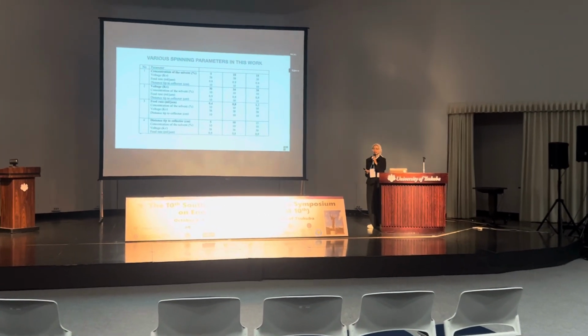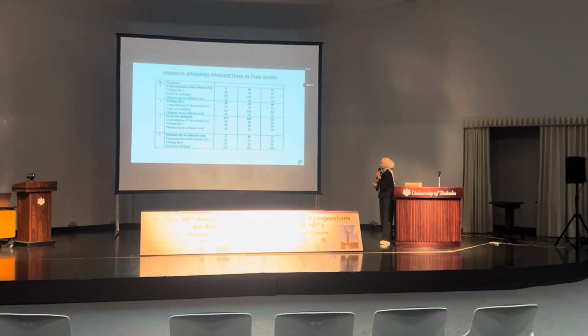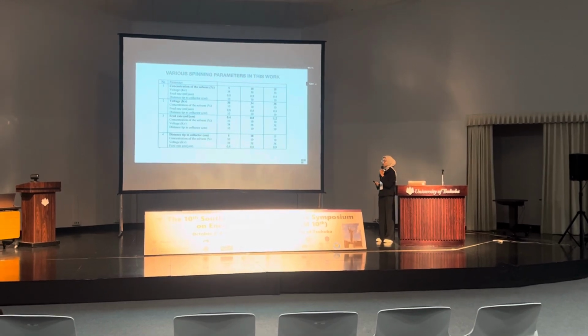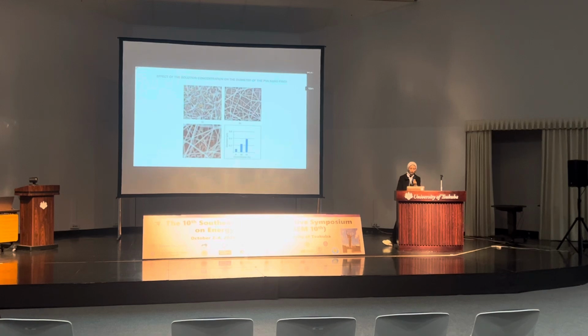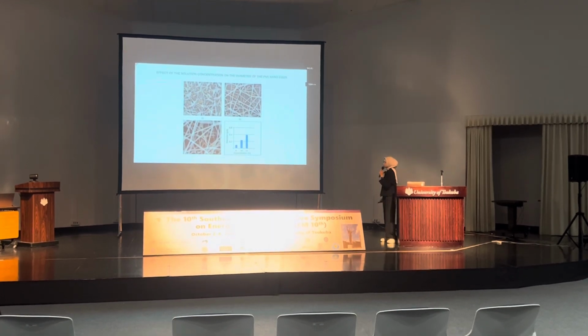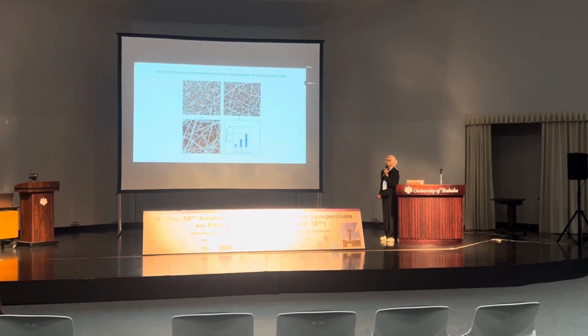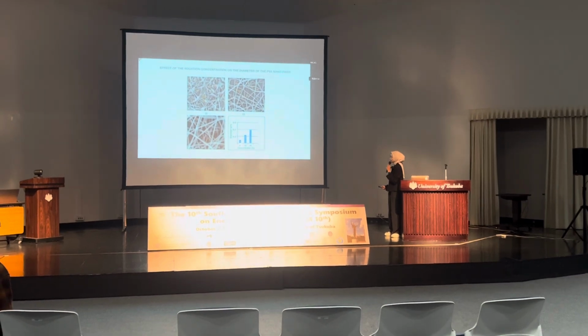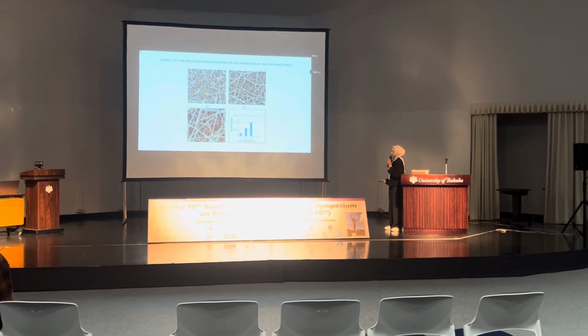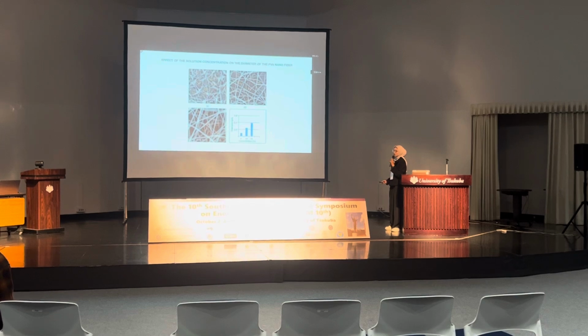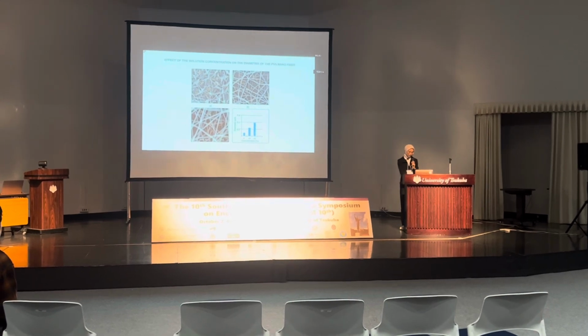By using the scanning electron microscope, the diameter of the nanofiber was investigated. Here are the results when the concentration of solution increased from 5 to 10 to 15%. It was observed that the diameter increased.